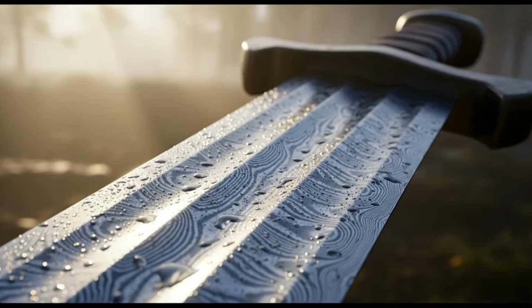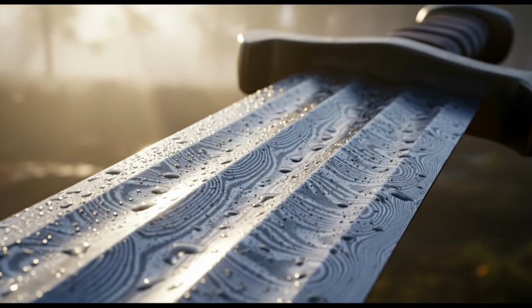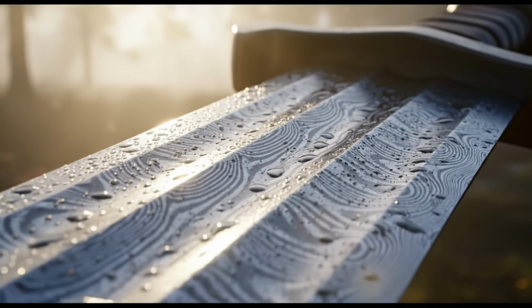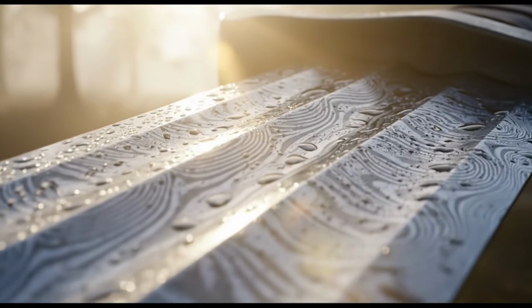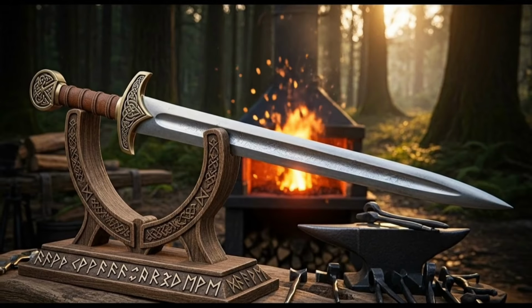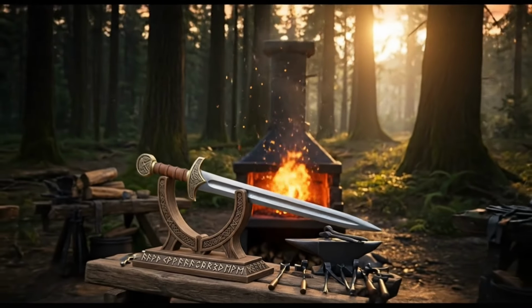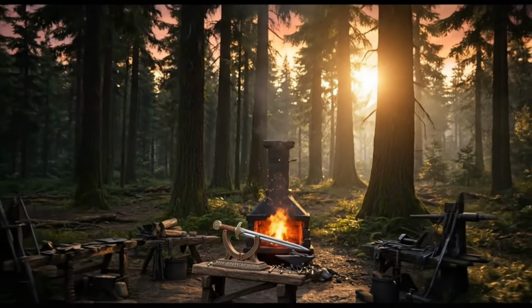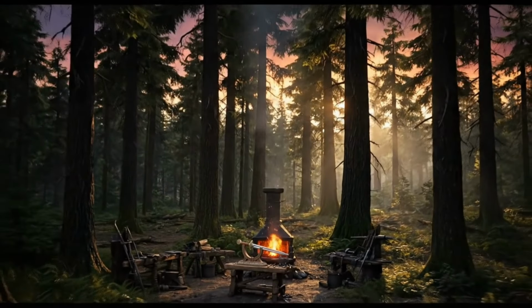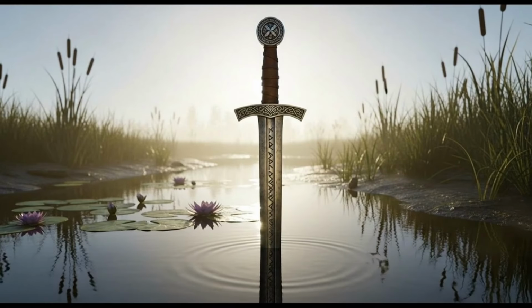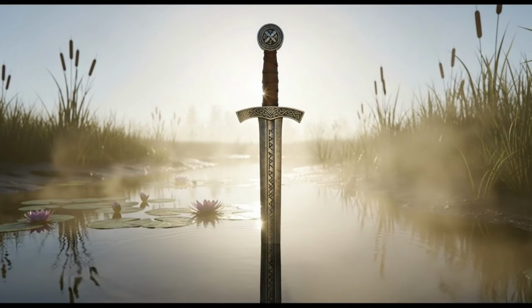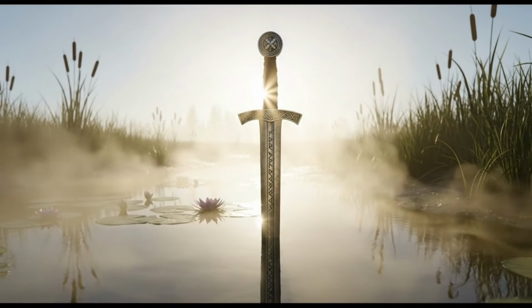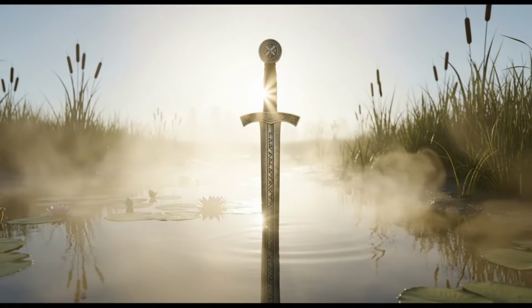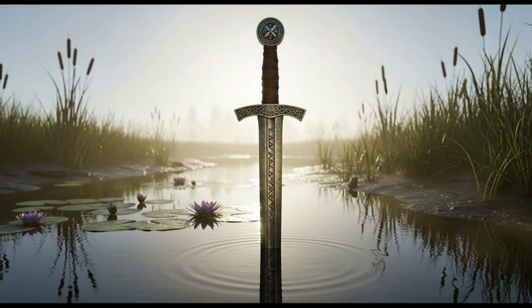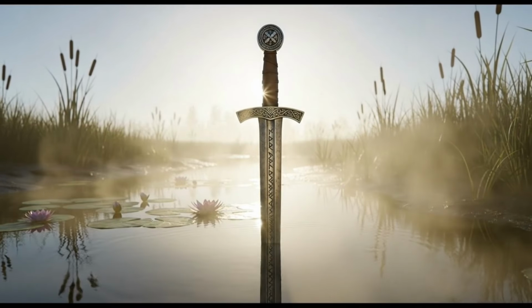After hardening, blades became as hard as glass and just as brittle. If someone tried to strike with it, it would most likely shatter into pieces. To relieve internal stresses and give metal necessary toughness and elasticity, a second stage was required: tempering. For tempering, hardened blades were heated again, but to much lower temperatures, around 200 degrees Celsius. At this temperature, so-called temper colors appeared on polished steel surfaces, ranging from light straw to blue.